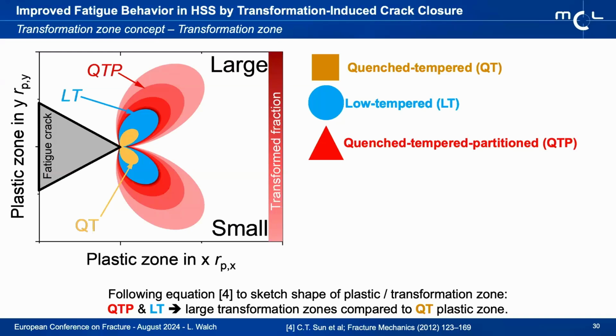If you look here at the quench tempered and partition material state, you'll notice that there's a color gradient, that should represent the behavior that we've seen before in the stress strain behavior, and especially in the behavior of the retained austenite content and its associated carbon content, that is this heterogeneity in retained austenite stability. Essentially, that means for any given stress field or transformation zone, on the outer edges of this transformation zone, only a small fraction of retained austenite is actually capable of transforming, whereas that fraction increases with proximity to the fatigue crack tip, or is at least expected to.